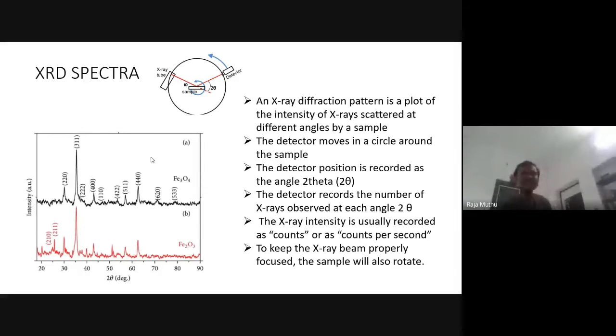See, there is a goniometer. The goniometer is a part of XRD, which consists of the X-ray tube, sample holder, sample and the detector. So this is the goniometer assembly. Here the X-ray tube emits the X-rays. Those X-rays fall on the sample, and the reflected X-rays will be detected by the detector. This is the simple assembly, right? The sample is placed over the sample holder, and the X-rays hit the sample. When the X-rays hit the sample, the diffracted pattern is identified by the detector. So this is the idea.